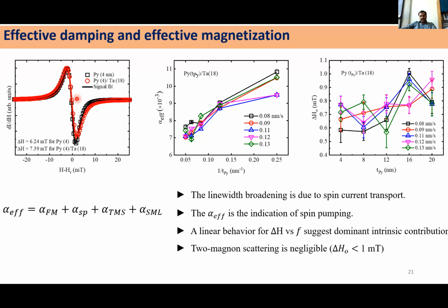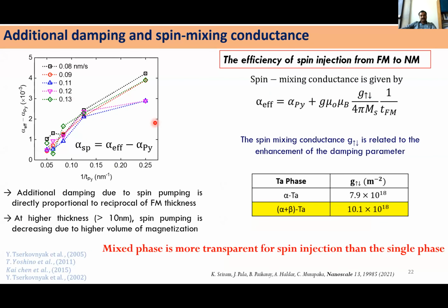Okay, so I'm not going deep into that, but let me tell you that there is a parameter called spin mixing conductance that talks about the amount of spin current that is transferred from the ferromagnetic layer to the non-magnetic layer, and that can be found from the additional damping coming in the ferromagnetic resonance spin pumping experiment. So for alpha tantalum, you can see that the spin mixing conductance is around 8 into 10 to the power of 18, whereas the mixed phase shows a higher spin mixing conductance.